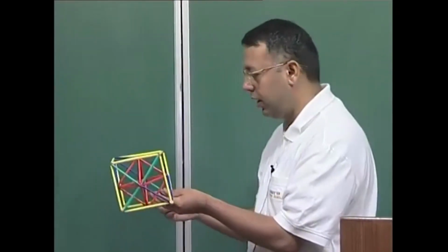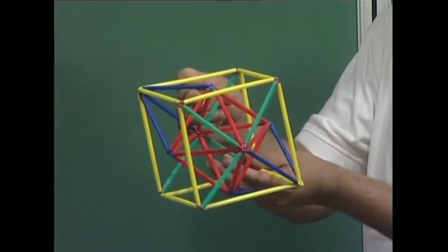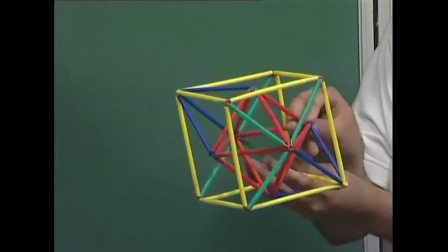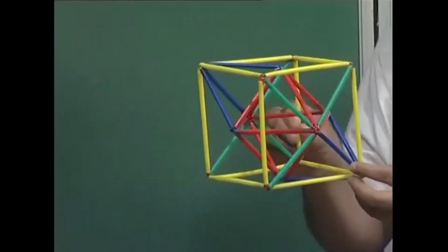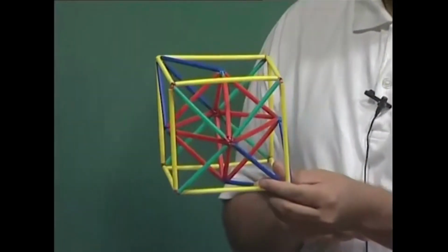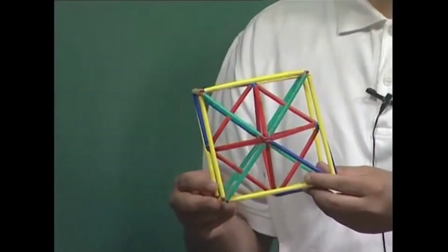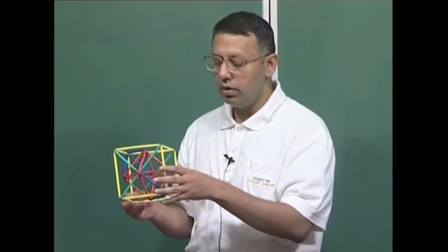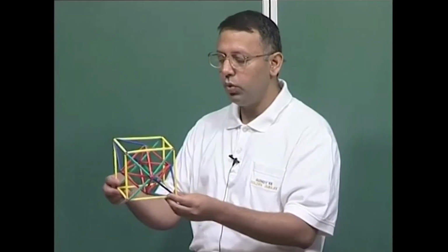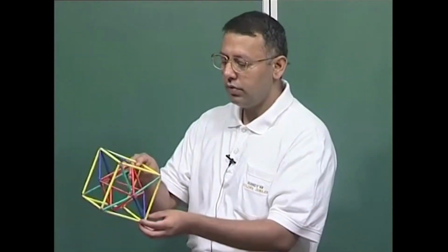So, let me rotate myself a little bit. In the green background you can see this is my blue outline, this is my red outline. So, this is my tetrahedron, and then you have the central octahedron which consists of 8 faces and which is centered at the 0, 0, 0 position. Later on we will see that these octahedra and tetrahedra can be the centers or the voids in the cubic close packed structure. So, you can clearly see this is now the rhombohedral unit cell which has got trigonal kind of geometry.